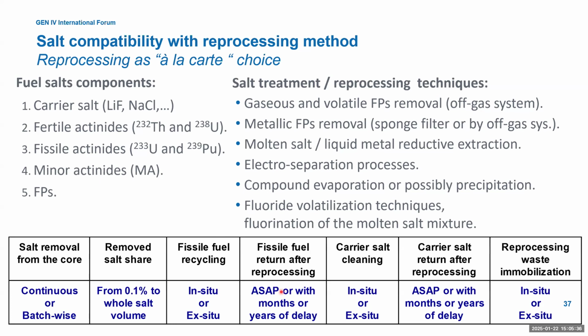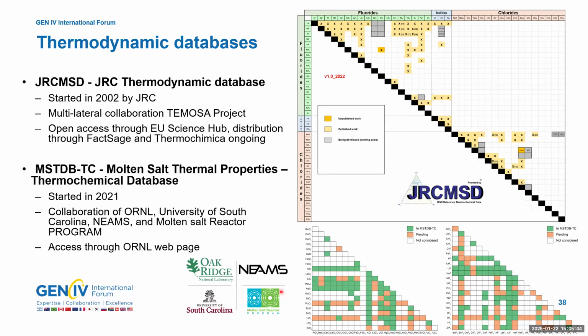Now, all that I said so far is leading to something which is needed, and it's a kind of database of salt parameters. So we have thermophysical and thermodynamic parameters, and here I illustrated with thermodynamic databases. The 2 most cited are the JRC MSD database, whose development started in 2002, so more or less with the first European MSR project, and is being developed by JRC. And the MSTDB database of the USA, developed since 2021 in collaboration of Oak Ridge, University of South Carolina, NEAMS, and the Molten Salt Reactor program. So those are very important databases which we need for the salt properties, and which to a certain extent influence